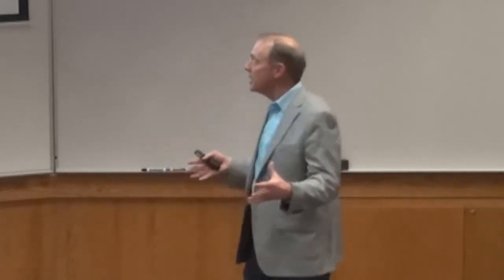We first thought it's because they were diffusing out of our interrogation volume, but we quickly did some calculations and figured out that couldn't be the case. What's actually happening is these electrons are recombining very, very quickly, and they're recombining at Shockley-Read-Hall recombination centers. The sample was mechanically polished, so there's a lot of damage, and so we get very fast recombination.